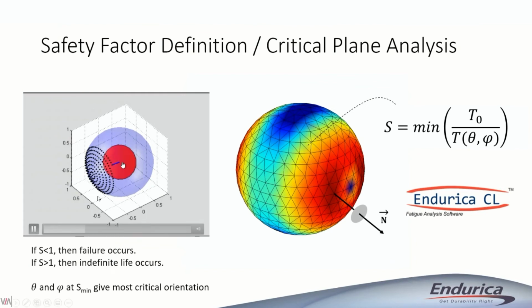This red disc here is a representation of a penny-shaped crack. And what we do is we repeat this calculation for all possible orientations of a crack in every element. And for each of these orientations, we say, if I calculate the energy release rate for that crack and I compare it to the intrinsic strength, what's that ratio? And we make a search to find the orientation of crack that minimizes that safety factor, because that's the most critical. And so this is what we call critical plane analysis, because we're searching for the particular crack that experiences the worst load case, and that's going to be the one that minimizes this safety factor.